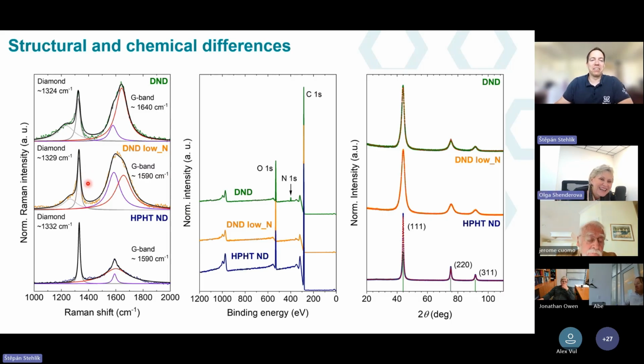So this tells that this is a structurally better diamond. I think it looks like the nitrogen somehow contributes to the broadening and the shift of the Raman diamond peak. And when we don't have nitrogen, or not that much, the peak can be a bit narrower and not that shifted, even though the particles are slightly smaller. So I think the particles are 3-4 nanometers in size in general. And here, these DNDs were about, I think, 5-6. So I think definitely these were made with the ice shell cooling. So that's definitely, I agree, one of the ways to control the size.